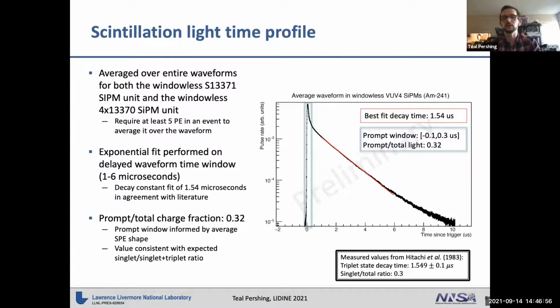It seems to be in agreement with some of the literature. Just some numbers from Hitachi from '83 are shown on the bottom right. And then for a first estimate of the prompt to total charge fraction, the window is shown in the image on the right. Using that window, the first prompt to total charge fraction is 0.32. So obviously we need to incorporate systematic uncertainties for the window that's picked and the pulse shape and whatnot. But for a first pass, it's looking like it's in the right neighborhood. So we're happy to see that.